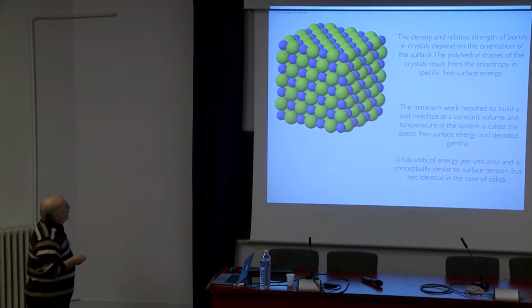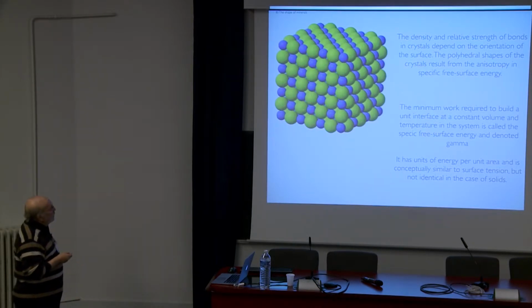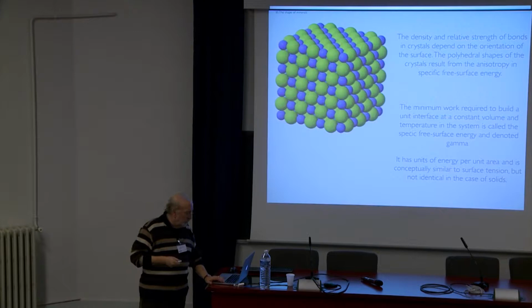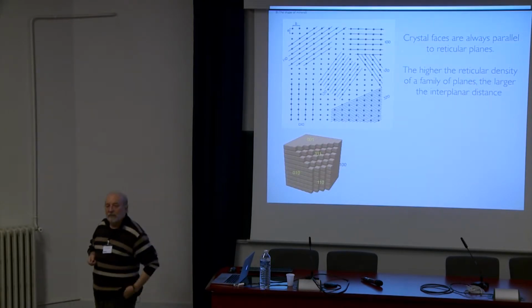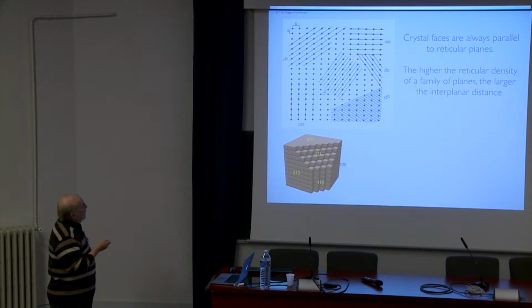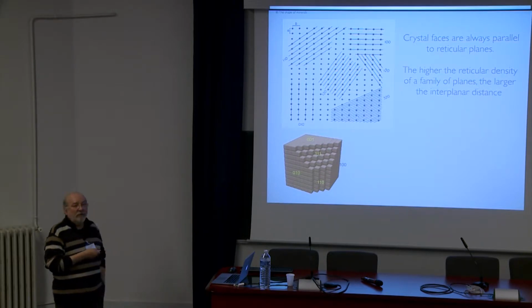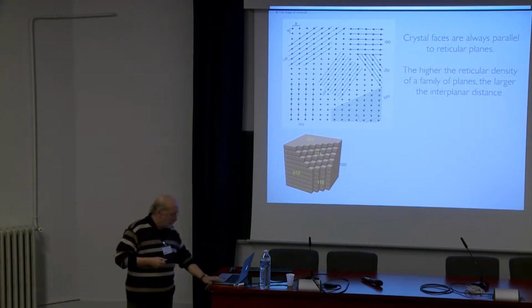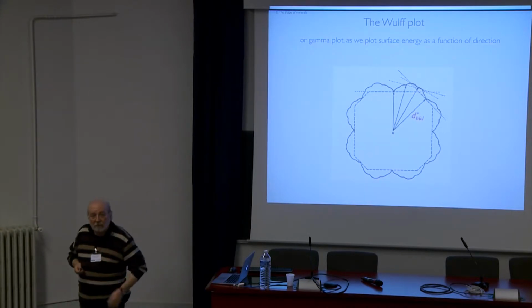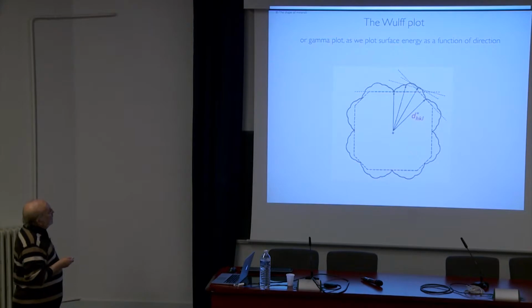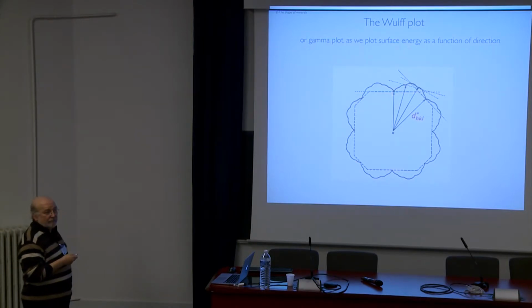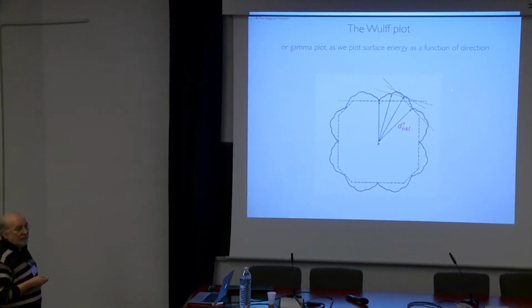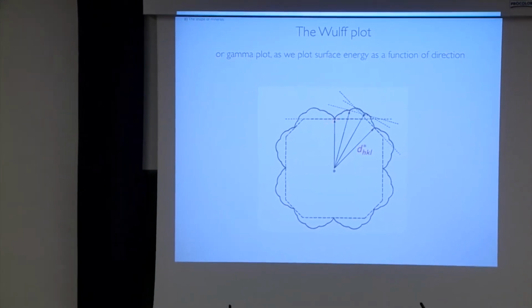Okay, you have a purely anisotropic material in which the property depends on the direction. So that the crystal grows. Okay, when the crystal grows, it will grow with different rates depending on the different family of planes, particular for each kind of face. So we like to use the Wulff plot. It's a plot that tells you that depending on the surface energy of the different faces of a crystal, you will have a final shape that is formed by the faces with minimum energy.